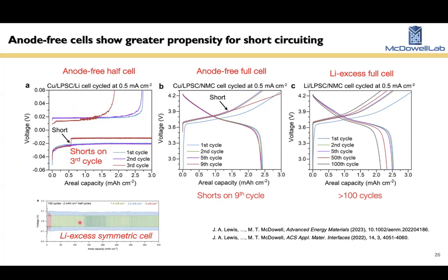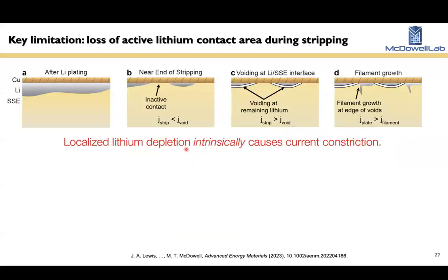And if we do the same test in a symmetric cell with lithium on both sides, we can cycle hundreds of times without short circuiting reliably. So clearly there's something different that's happening. Same thing in full cells, where here we're short circuiting within the first 10 cycles. That's very common. Whereas with excess lithium full cells, we can cycle over 100 times without short circuiting. So something different is happening here.